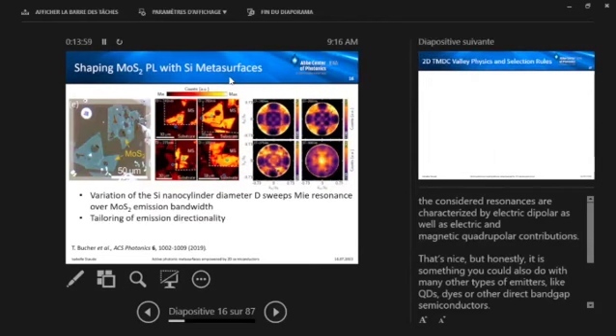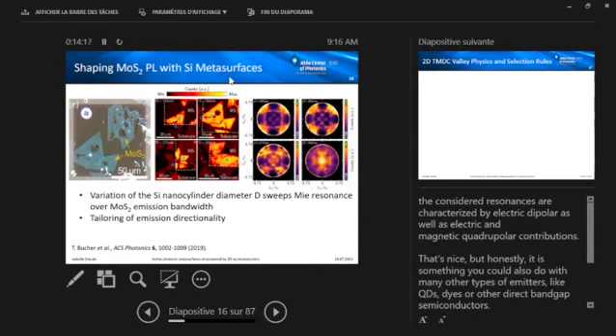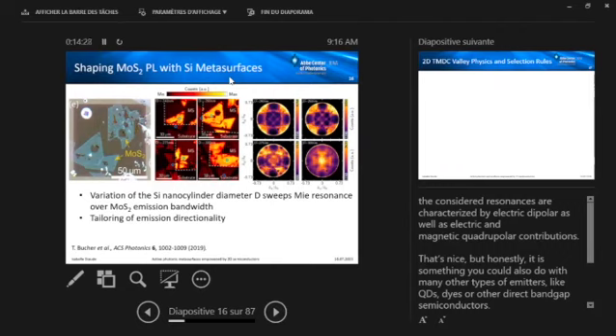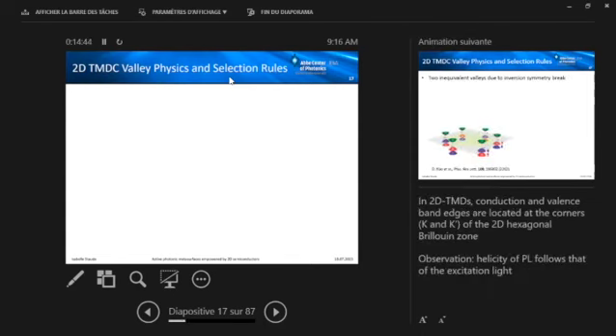And here we come to the shaping of the light emission, and what I show you are back focal plane images of emission. So basically, each point here corresponds to directionality of emission, the center being the out-of-plane emission of the metasurface plane. So if we now change the diameter and sweep the Mie resonances in overlap with the emission of the TMDC, then what we see is that from this more sideways-directed emission, we move to a more out-of-plane emission. Okay, so this can be tailored, and that's sort of nice. But in principle, you can do this with any other emitter, there's nothing special here about the TMDC.